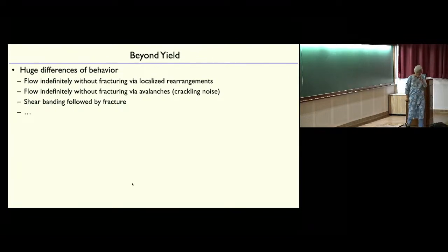But now, if I go beyond yield, all hell breaks loose. You lose that universality. Different systems do different things. So the foams that Doug was talking about, he found that the rearrangements remain localized always. You don't get avalanches, you just get these isolated localized rearrangements and the foam will flow. In other systems, you get avalanches. Still other systems, you see shear banding. So the shear becomes localized instead of the whole system flowing.